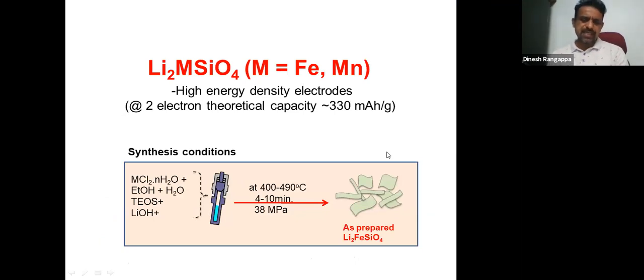After realizing lithium iron phosphate under supercritical fluid conditions, we tried to develop lithium 2 metal silicate, which is a 2 lithium capacity material. Because of this, from the 150 to 160 range, we can realize a 330 milliampere-hour per gram capacity cathode material, which is the theoretical capacity. However, due to amorphization and structural instability, this material gives only one electron capacity, so one lithium capacity. Then we adopted a two-dimensional nanosheet structure strategy, and we could demonstrate two lithium capacity. Still, we need to improve the cyclability of this material, and we are working to make it more stable.